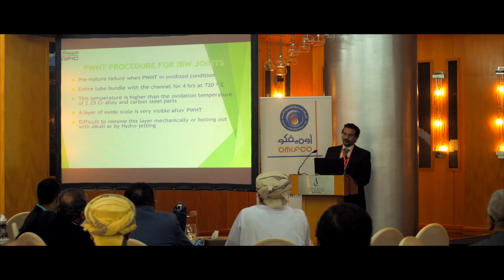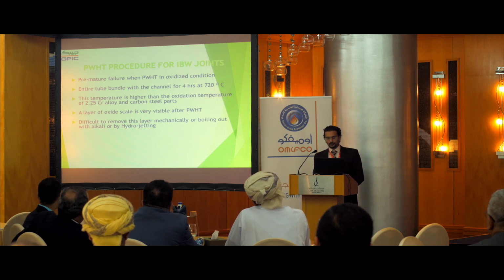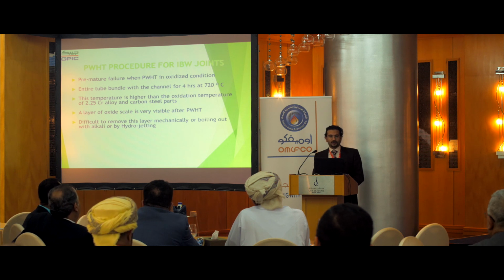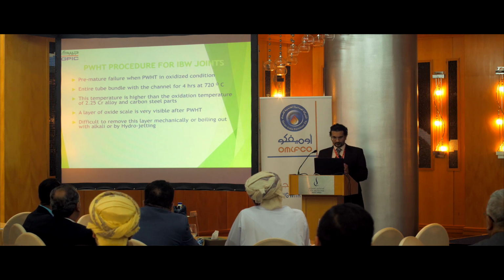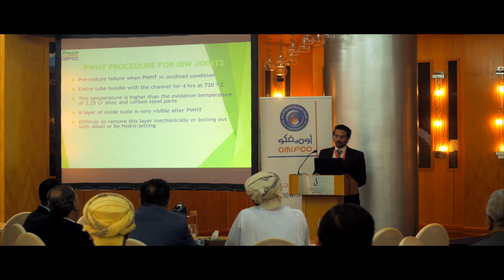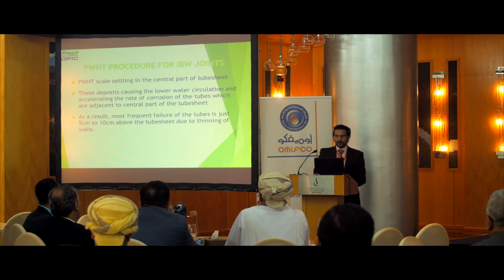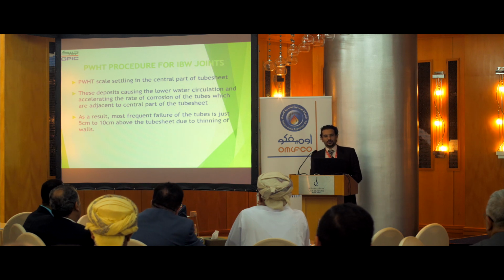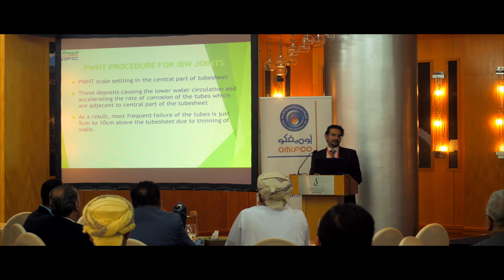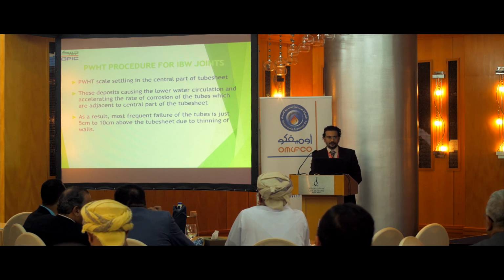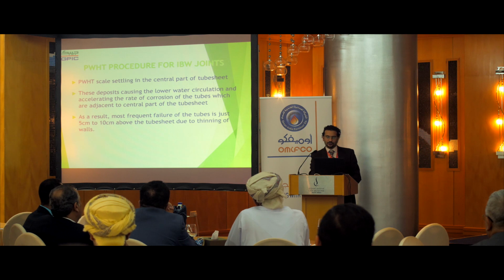So the post-weld heat treatment for the IBW joints for our earlier waste heat boilers, premature failure when the post-weld heat treatment was in oxidized condition. They seem to find some scale on the tubes afterwards, which was hard to remove mechanically, with alkali or hydrojetting. And this scale was settling in the central part of the tube sheet. It causes lower water circulation and accelerates the rate of corrosion under deposits. And the most frequent failure of the tube is just 5 centimeters to 10 centimeters above the tube sheet.